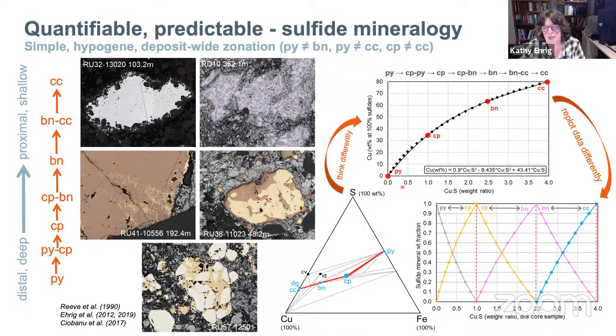But then we change it back into a world where metallurgists speak a little bit, and they speak of the rock in terms of the copper to sulfur ratio, which is really a proxy for these sulfides and what the grades are. And what we can do, if we have a rock that has 100% sulfides in it, is plot mixtures of all four of these sulfides together, one, two, three, or all four of them, and they're going to plot along this curve here.